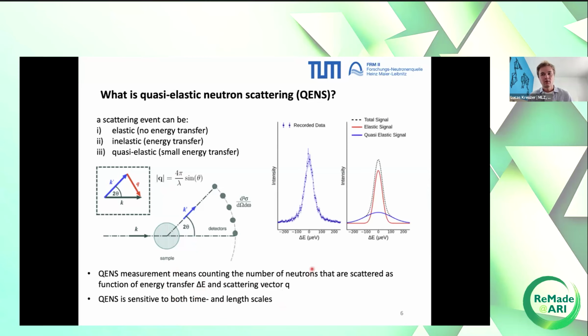Now, a typical QENS spectrum would look like this. You have the intensity as a function of energy transfer, and this data is comprised of two things. So first, the elastic line, here shown in red. In a perfect experiment, in a perfect instrument, this would be just a line, the elastic line. But you all know science isn't perfect. Instruments are not perfect, so we have a certain resolution, and this would be the resolution limit of the instrument, the broadening of this elastic line. And then there's the quasi-elastic signal, where we would detect the quasi-elastic scattering signal, where the quasi-elastic energy transfers are happening.